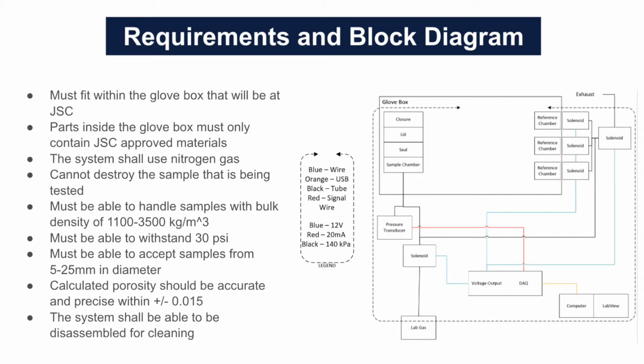Other requirements are that the system shall use nitrogen gas, cannot destroy the sample, must be able to hold samples with bulk densities in a given range, must be able to withstand 30 psi, and must be able to accept samples from 5 to 25 millimeters in diameter. The thresholds for our accuracy and precision of our porosity are plus or minus 0.015. Finally, the system must be able to be disassembled for cleaning by NASA.